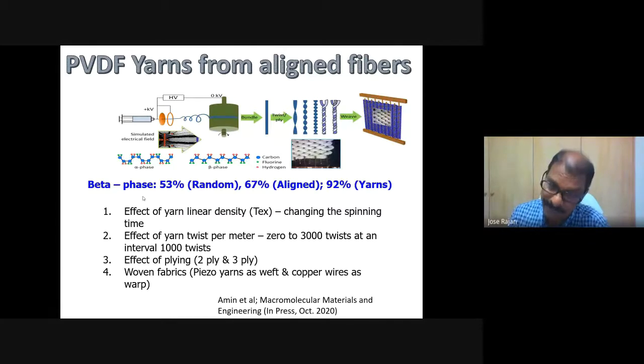For example, when they are woven into a piezoelectric fabric using weft and warp. Here we used copper wire, very thin copper wire, about 30 micron thick, as the warp electrodes, and these piezo yarns are the weft. We have developed these textiles here. That's what you are seeing here, and we systematically investigated what their effects are. The results are summarized in this table, in this slide.